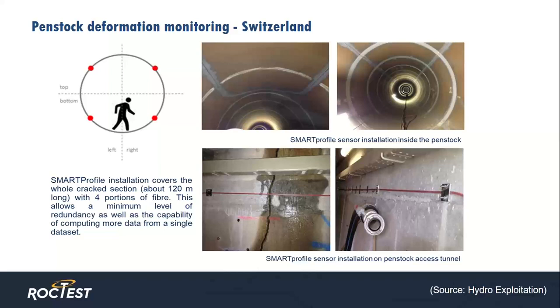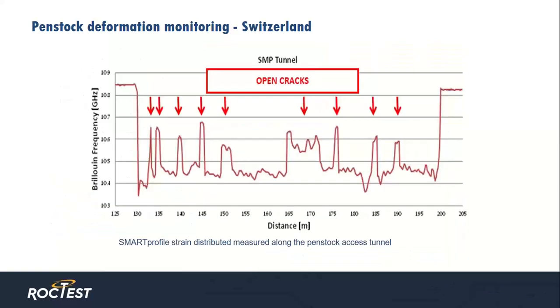The bottom two photos, you can see a good depiction of what was going on in the concrete access tunnel. Large crack here. And in this instance, the smart profile was installed using metal and plastic clips. Okay, in this Brillouin frequency versus distance plot, you can see where the cracking occurred along the concrete access tunnel. Each one of these peaks corresponds directly to one of the cracks in the access tunnel.